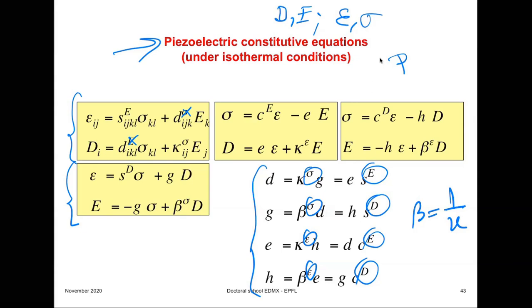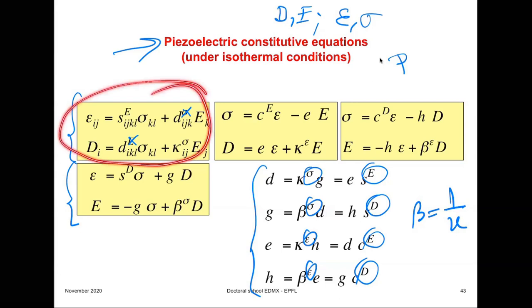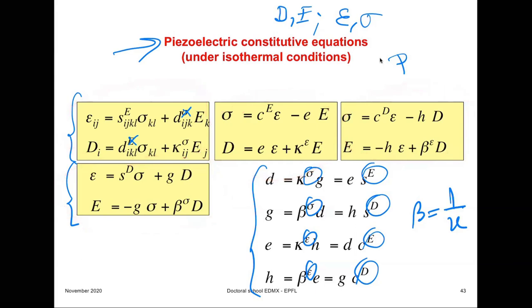In materials with very small permittivity this could be different. In any physical problem at constant temperature, you must use the full set of constitutive equations. You must consider not only the variables you are changing and applying, but also those variables that may arise in the system because of the boundary conditions — I will give examples of that later for thin films. Whichever set of constitutive equations you use, you will eventually reach the right result, but choosing a set inappropriate for your boundary conditions makes the equations very complex, sometimes impossible to solve.